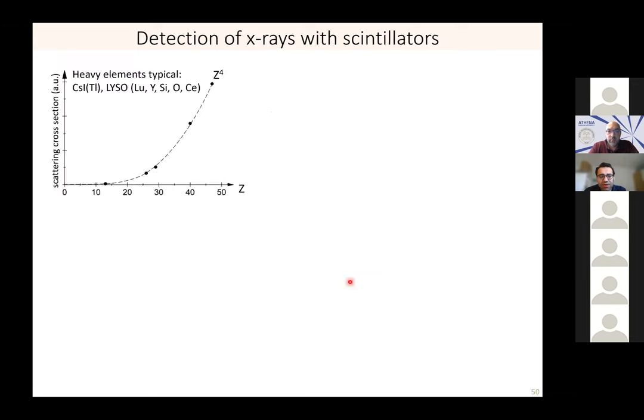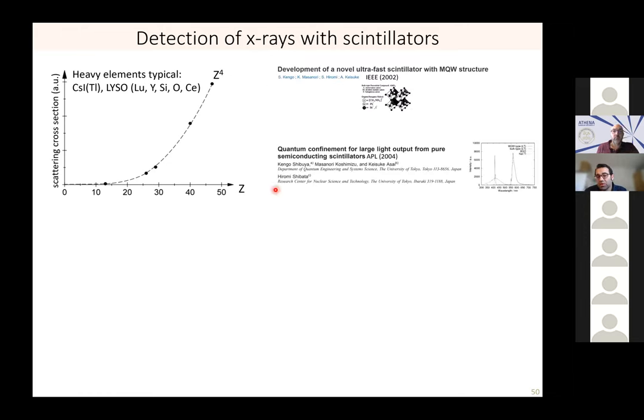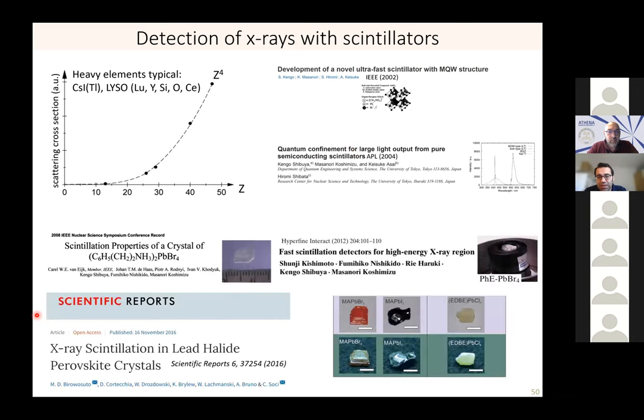And why could perovskites be interesting? Because the scattering cross-section increases with the atomic number, so the heavier the better. So Z equals 14, which is silicon, doesn't suit it. And here, all of a sudden, there's a unique advantage for perovskites. And as always, I haven't come up with this idea. If you want a new idea, you look into old papers. A lot of it has been reported in the 2000s. You see here how these perovskites, 2D perovskites in that case, have been looked at for their scintillation properties.